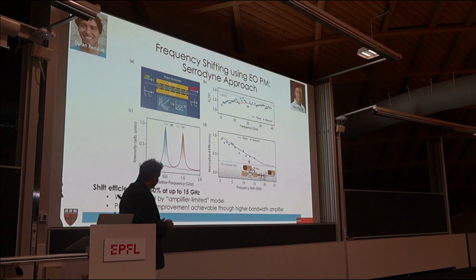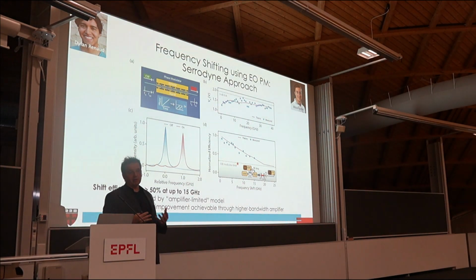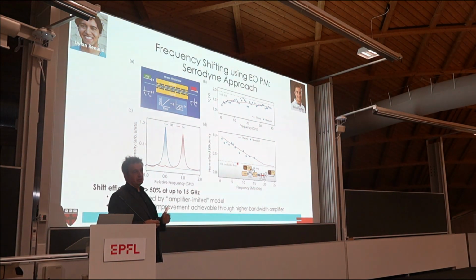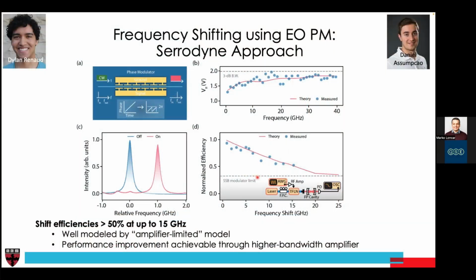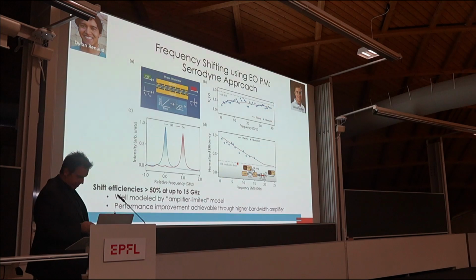And this is still better, even though it has pretty high loss. It's still better than the alternative technique, which is to use a so-called IQ modulator to do the same thing, to generate two sidebands and then filter one and keep the other one. So this is still efficient. And if you had better electronics, you would be able to make this more flat. And you can learn more. Unfortunately there's no reference here, but this paper is also on arXiv.